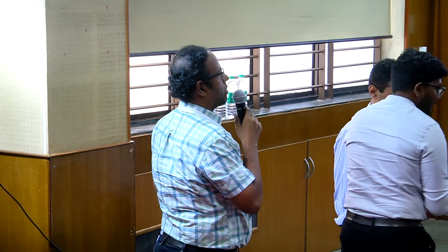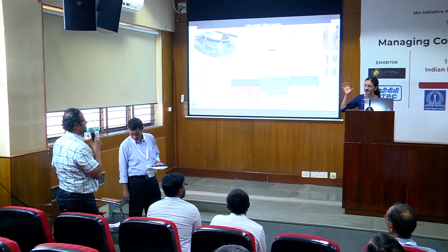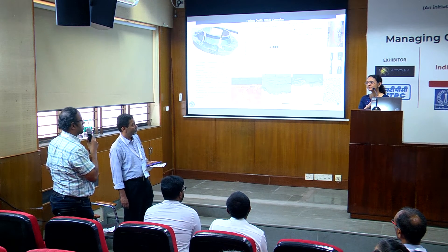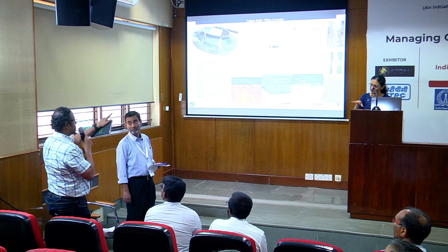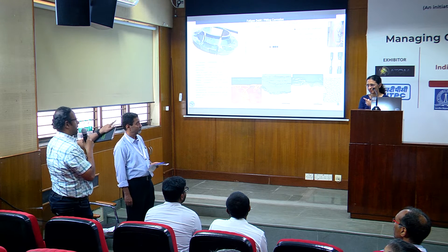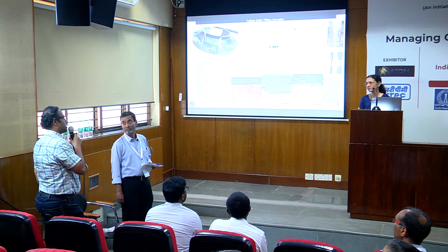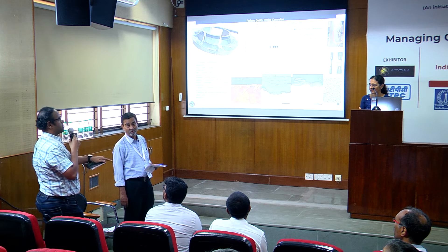I'm Lakshman from IIT Madras — very nice presentation. On similar lines, do these alloys have a pre-oxidized film on top? What we showed — except for the aero engine disc — the blade and others almost all have an oxidation bond coat. Many of them at stage one have a top coat which is a ceramic. My question is: when you did this analysis of random pitting — this is type 2 corrosion if I understand correctly — don't you expect that the first phase of change would be on oxide growth, and then it sets into the fluxing of sulfur to produce non-uniform pitting?